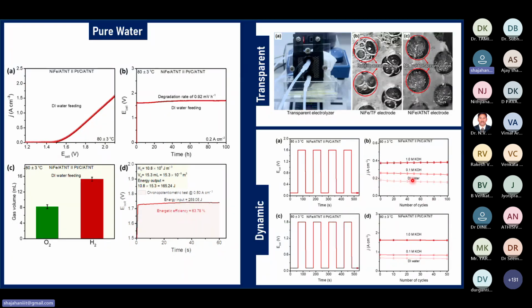So with different electrolytes, DI water, 0.1 molar KOH solution, 1 molar KOH solution, we tried different electrolytes also. So we observed very limited degradation. The positive thing is the electrolyzer didn't die. Usually when you run this kind of experiment, the electrolyzer at lab scale generally dies. But here, it is showing very good performance. It is responding with good performance like PEMWE. So that indicates it is also best suited for industrial scale if you make this kind of setup.